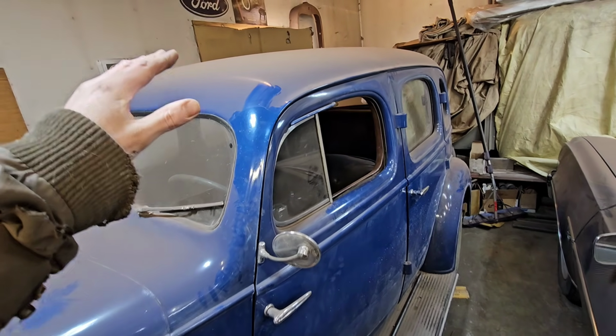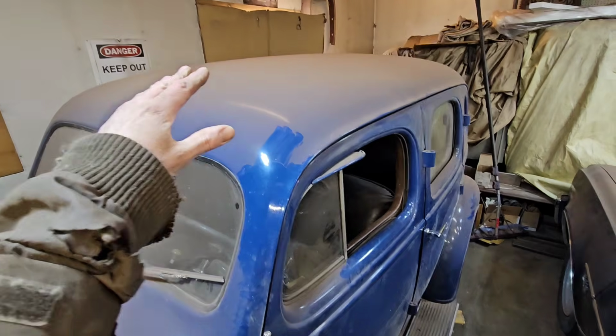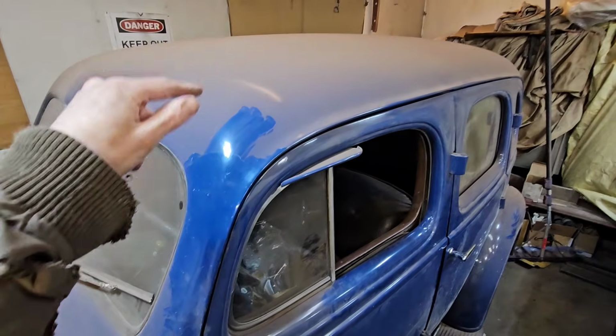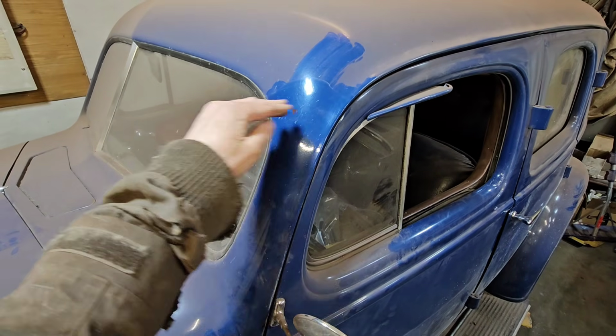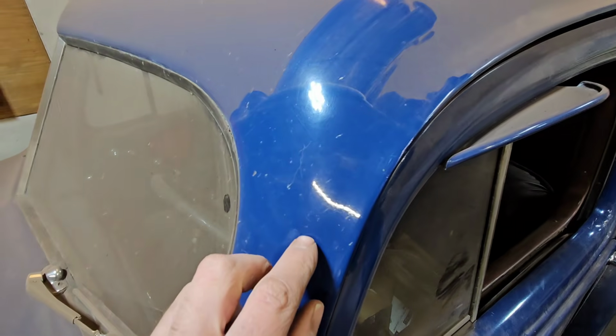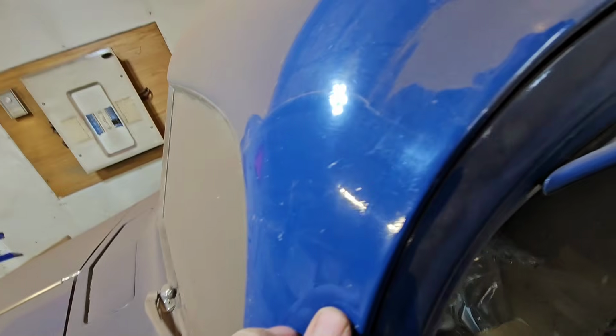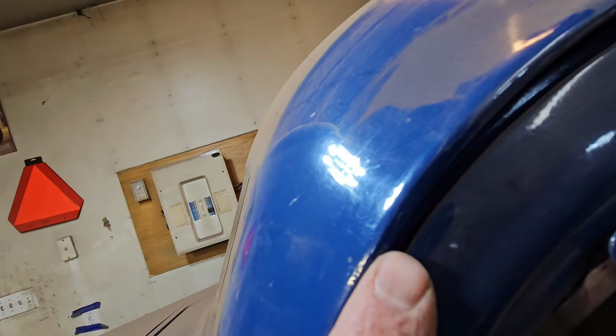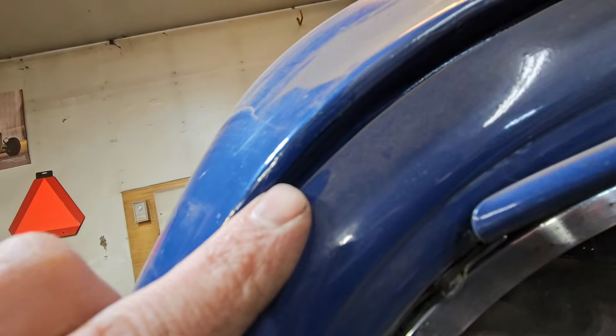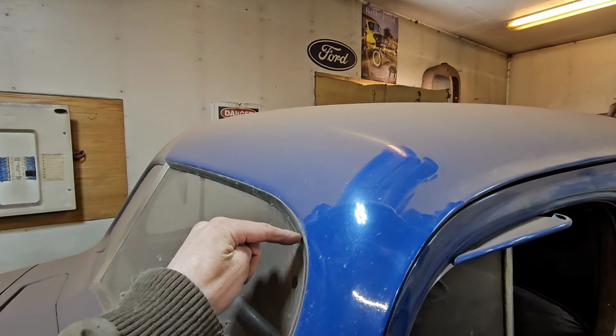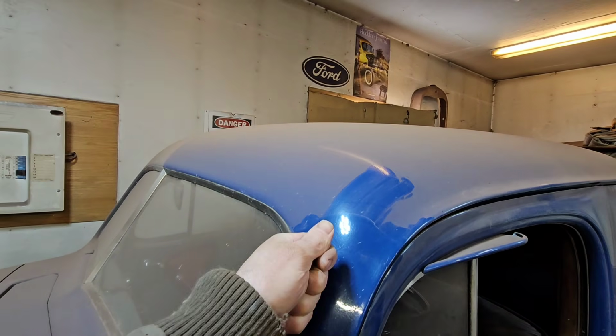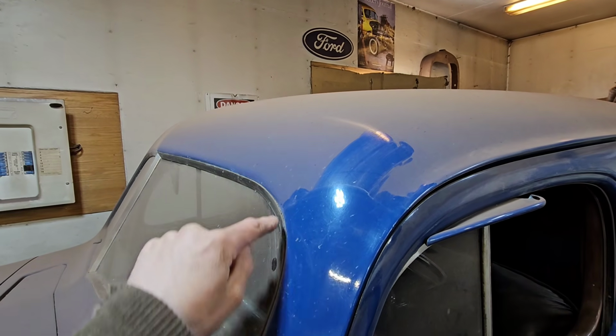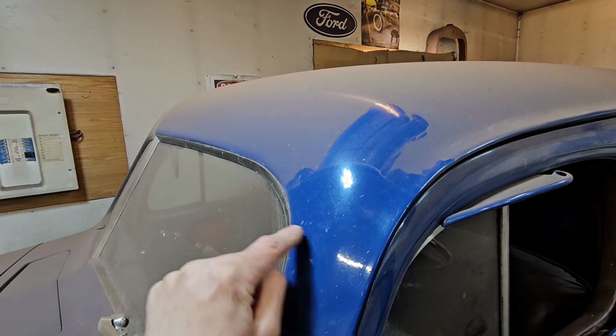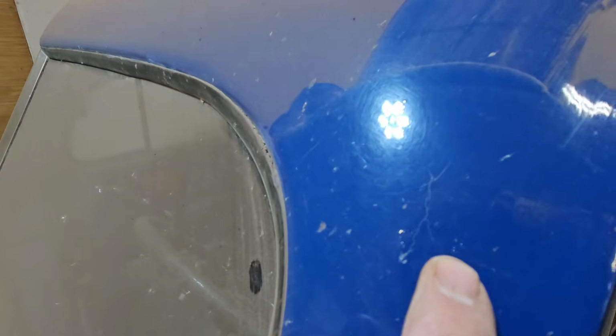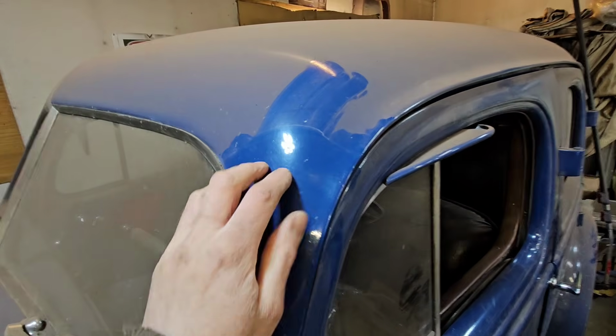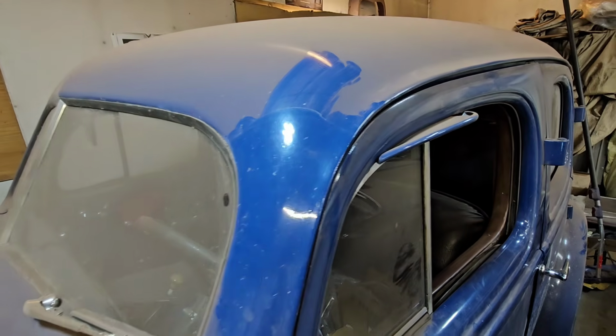This was the first year for any car to have an all steel roof, and this roof was lap welded onto the lower A-pillar right here. And if we look closely, you can see this crack here, and I don't know if it's going to show up on camera or not. There's another crack right here. Again, this was lap welded here, beaten down fairly severely, and then filled with lead. And now, if we melted this lead out, there would be rust under here, which is what's causing this lead to crack. And how bad is it? I don't know, and I don't really care to find out.